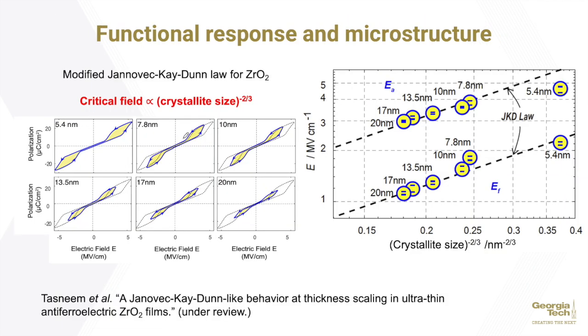And these microstructural features actually have an important role in determining the functional response. For example, in zirconia, we changed the thickness from 5.4 nanometers to 20 nanometers. And we also determined the crystallite size using glancing incidence X-ray diffraction. And we could clearly see that the critical fields have a negative 2/3 power law dependence on the crystallite size in these materials. So overall, microstructure plays a central role in determining the functional response of these materials.